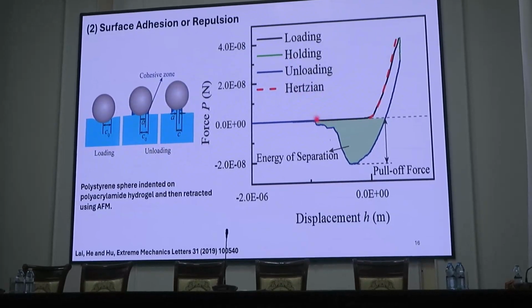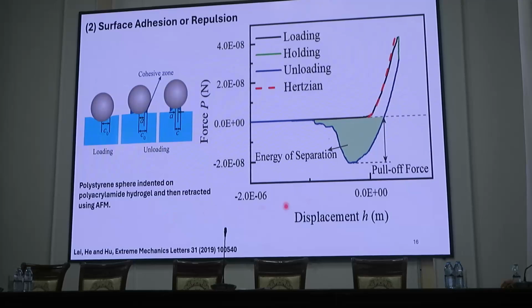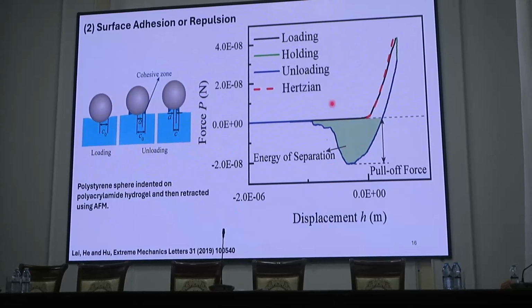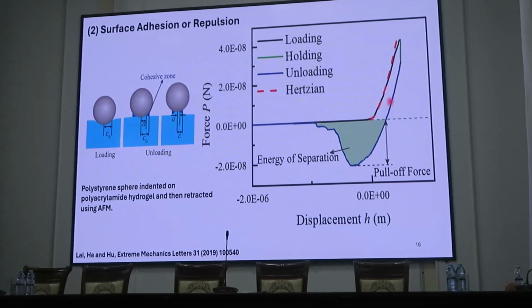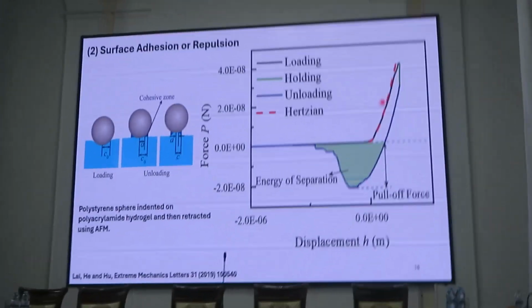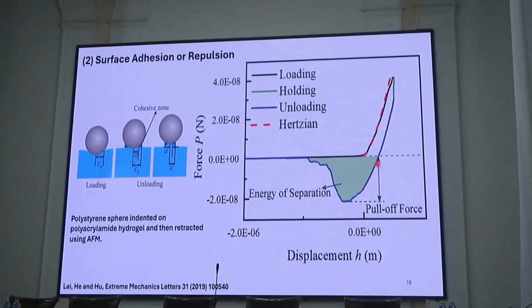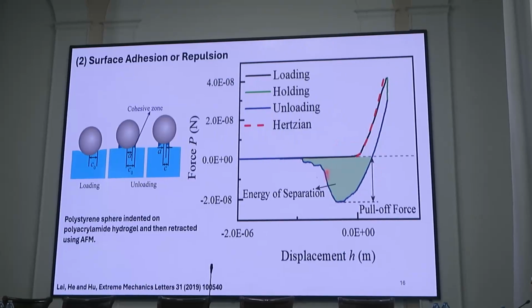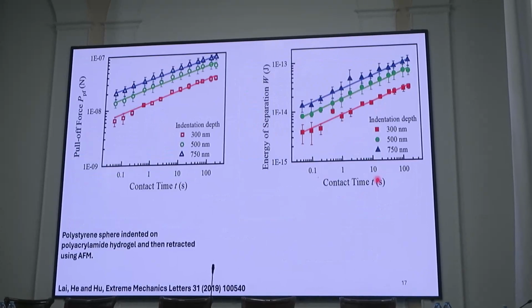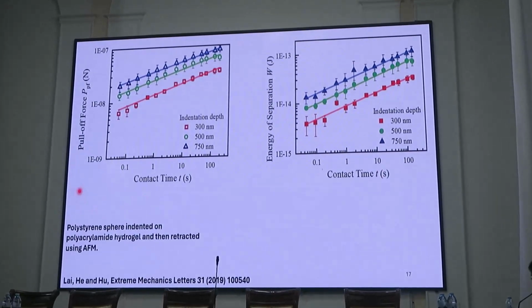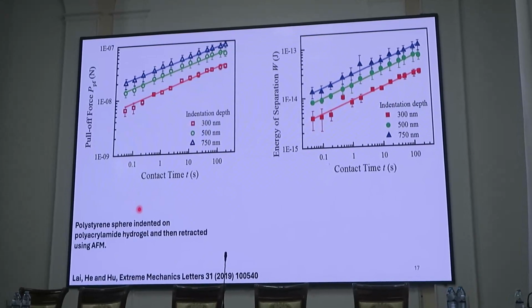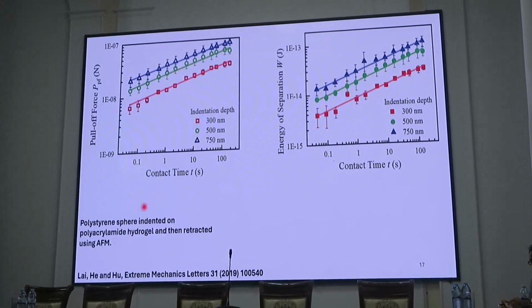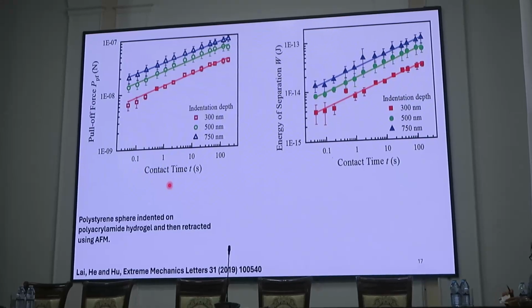Many people have done work on hydrogel. So this is work on hydrogel, and there is a huge amount of adhesion. This is the indentation, reverse loading and unloading, and you can see that the energy of separation is quite large. Then the pull-off force depends upon so many other factors, for example, contact time, how long it has been in contact.